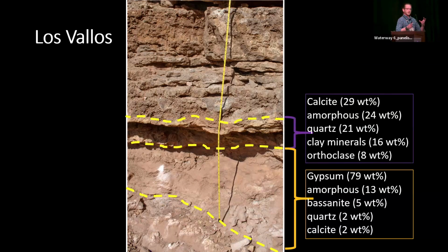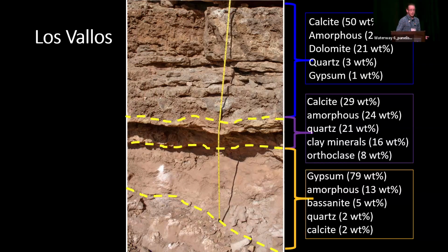Above that, we see this sort of gnarly layer with calcite, amorphous material, quartz, and a lot of clay minerals. We haven't completely nailed down what the clay minerals are, but it's most likely mica, illite, something like that. So we suspect that it's detrital rather than authigenic because we don't see any other evidence of high temperature stuff ongoing here. So probably detrital clays with a bunch of calcite. And on top of that, these blockier, better consolidated layers are mostly calcite and dolomite with a good deal of amorphous material. And again, a little bit of gypsum, which we think is probably contamination from all of the other gypsum that's blowing around in this area. All right, that's what we found.